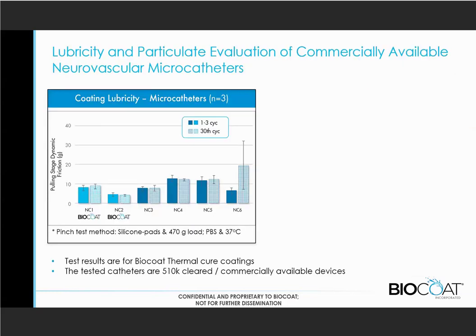So let's take a look at this. This is for the neurovascular catheters, where we're looking at the lubricity. Just to walk you through here, there were 6 different manufacturers and brands of catheters we used. 2 of them we knew were Biocoat customers and had Biocoat coating on them, but the other 4 did not. And so we evaluated all of those. We looked at 30 cycles that we were pulling these through this vertical pinch test, and measured both the initial cycles and the 30th cycle.